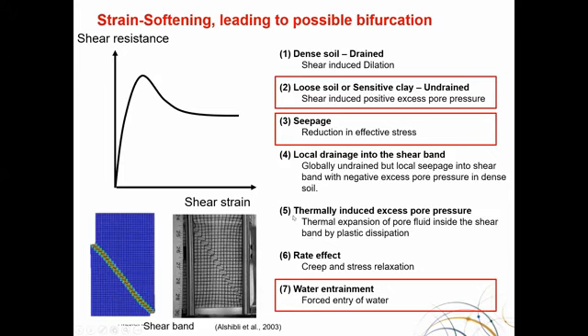The energy dissipated inside the shear band has to be converted to heat, and there will be local thermal expansion of the soil. Since the thermal expansion of the soil skeleton is smaller than that of the fluid, excess pore pressure can develop in undrained conditions, which in turn softens the shear band. This was discussed in the recent Rankine lecture by Professor Eduardo Alonso. The rate effects of soil, including creep and stress relaxation, will lead to structural softening, and the forced entry of water will also soften the soil. In this presentation, I'll show some simulations of the ones highlighted in red.